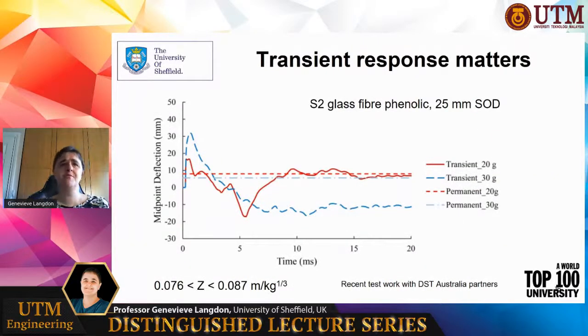So if we were to look at those same panels now, but we change the standoff distance, make it lower, make it more localized, but we reduce the mass of the charge as well, then we can get to a position where if you look at the 20 gram pulse, you can see that you get a lower peak displacement in the direction of the blast, around 18 millimeters, and then a higher peak in the opposite direction, which is really interesting. And again, is an illustration of this phenomenon of buckling.